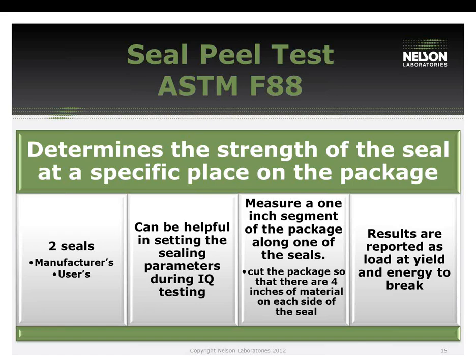You can also use the seal strength test to help set your IQ parameters for your sealers. The way that the process works is you measure a 1-inch segment of the package along one of the seals, whether that's the manufacturer's or yours, and you cut the package so that there's approximately 4 inches of material on each side of the seal. We take this and we put the seals in an Instron or tensile tester, and we pull the sample apart. The results are reported as load at yield, energy to break, and they'll give you a value. This is a quantitative value.